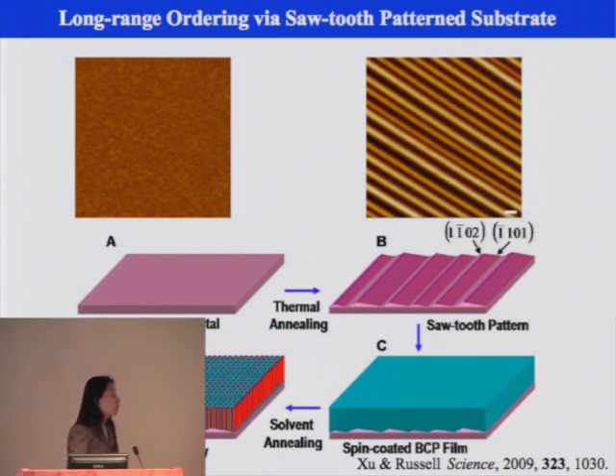So we went to a lab, we tried it, and it turned out to be really good. We were using sapphire as an example. This is an AFM image of a miscut sapphire. It's fairly smooth. You heat it, you bake it at about 1300 degrees, and what do you see under the AFM image? You can see different ridges come out. We call it a sawtooth pattern. What's interesting is that you see the pattern goes in one direction.